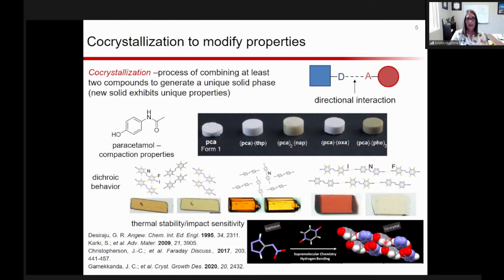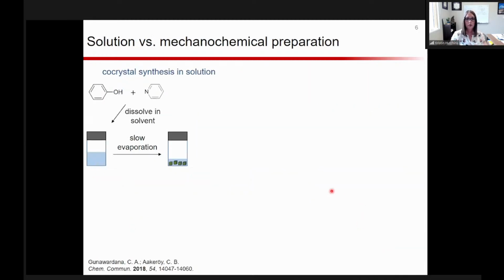And so when you think about making co-crystals, you can make them via a variety of different ways, but I'm going to walk you through the 2 ways that my group typically makes them. And one of those is by solution methods. Let's say you have 2 simple molecules here that you might expect to interact by hydrogen bonding. By solution methods, you would dissolve those 2 components in a solvent in which they're both soluble. And there is some tuning that goes into that selection. So you're going to fully dissolve them. You might need to use heat or sonication to get them fully dissolved. And then you're going to allow that solution to evaporate slowly over time.